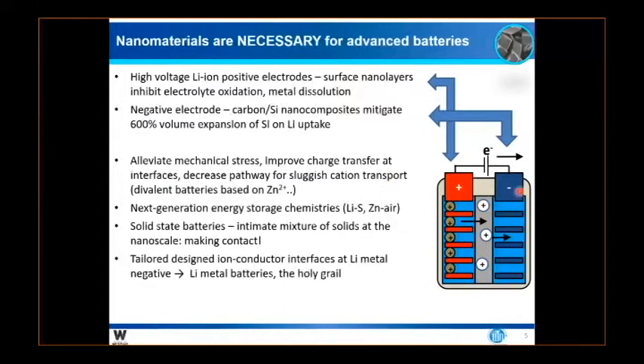And the negative electrode, as I mentioned, silicon is now replacing carbon in the form of these nanocomposites where the carbon and the silicon have to be intimately mixed. And this is necessary because silicon expands and contracts tremendously on lithium uptake. And so the nanotechnology is needed to control and mitigate that expansion.